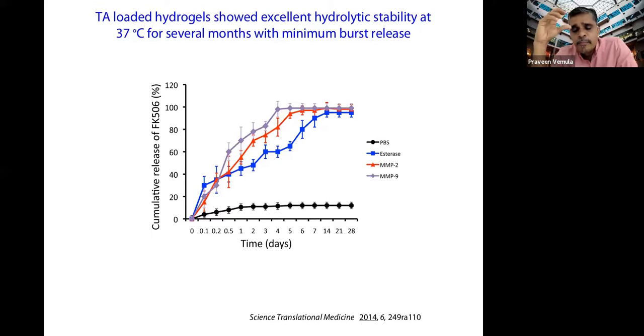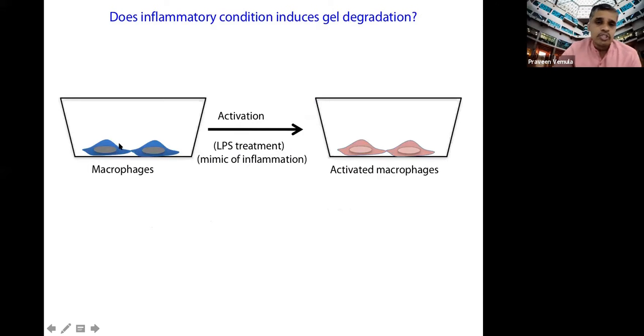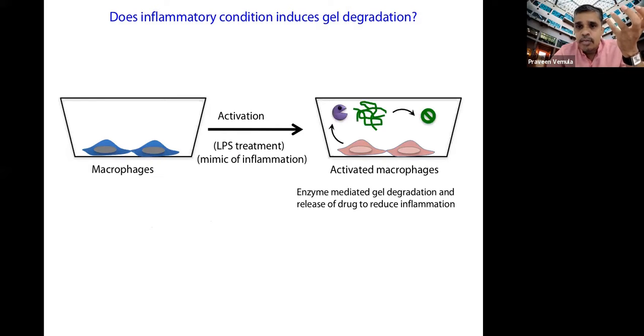Then we wanted to see whether we get a similar response to inflammation as well. To test that, we took macrophages, which are our immune cells, and you activate them with LPS treatment. These activated macrophages resemble your inflammation-like condition in the body, and they're known to produce these proteolytic enzymes. Then we wanted to see whether these in situ generated proteolytic enzymes can degrade the gels to release the drug. To test that, we took the conditioned media from activated macrophages, as well as non-activated macrophages as a control, to see the release of the drug.